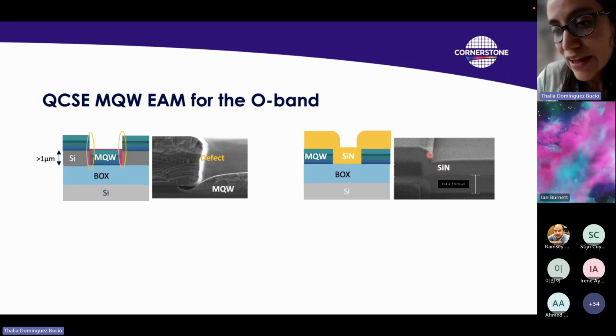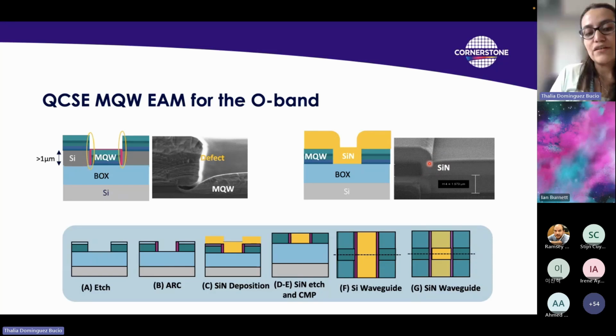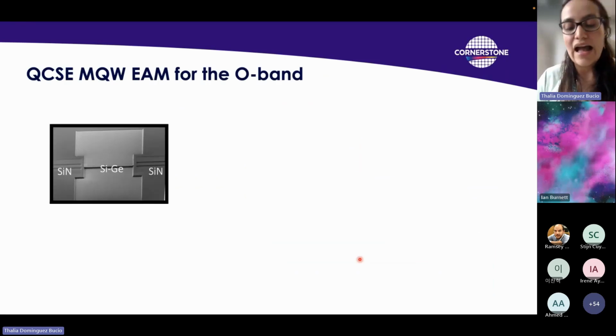Because if you do it that way, you get a smooth transition between the two materials. So in this case, to achieve this, you will have to etch your multi-quantum well stack, deposit an anti-reflective coating, then you can deposit the silicon nitride, and then you can etch the nitride and planarize it, and then you can etch your waveguides in both materials. In such a way, it is possible to achieve the integration of silicon germanium multi-quantum well waveguides, smoothly and simply integrated with silicon nitride waveguides.